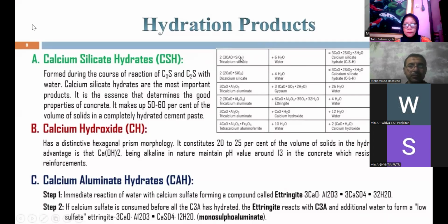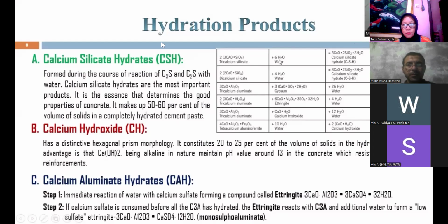The difference between these two phases is the amount of portlandite, or calcium hydroxide. The amount of portlandite liberated from the reaction of tricalcium silicate with water is triple the amount of calcium hydroxide or portlandite liberated from the reaction of dicalcium silicate with water. CSH in total makes about 50 to 60% of the volume of the solids in the complete hydration of cement.